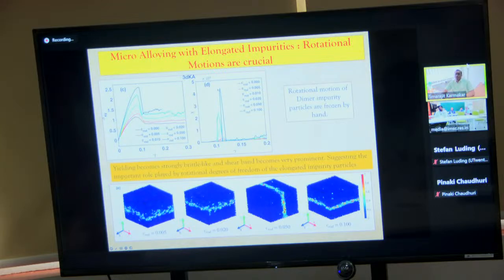The susceptibility peak went up by at least a factor of 10 to the 4, which is huge, which tells us that the rotational degrees of freedom of these dimers are extremely important for promoting or stopping this shear band formation. So when they cannot rotate, they somehow localize all the strain to form shear bands, which you can see in this snapshot. When you have some amount of dimers, then you have some shear band, but the shear band is somewhat diffuse, in the sense that its width is significantly large.